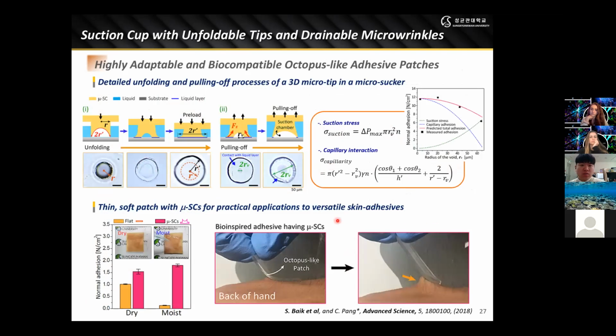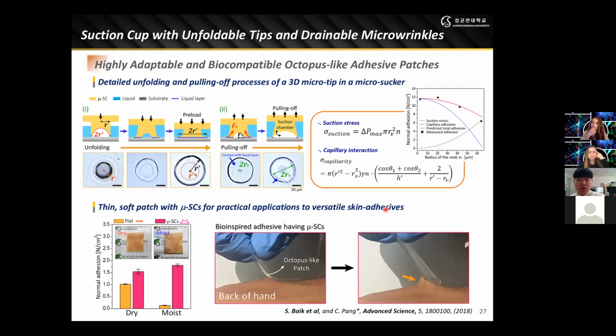We investigated with experimental and theoretical studies to increase the effective contact area. This adhesion force is mainly attributed to suction stress and capillary interactions between unfoldable microtips and the engaged surface. Our adhesive demonstrated stable attachment on moist and hairy skin having dual roughness. So we compared it with an adhesive without octopus-like structures.